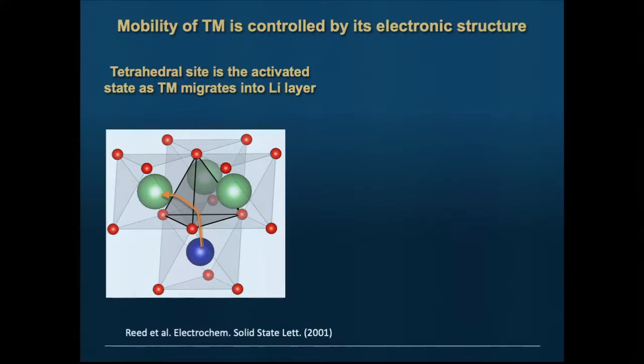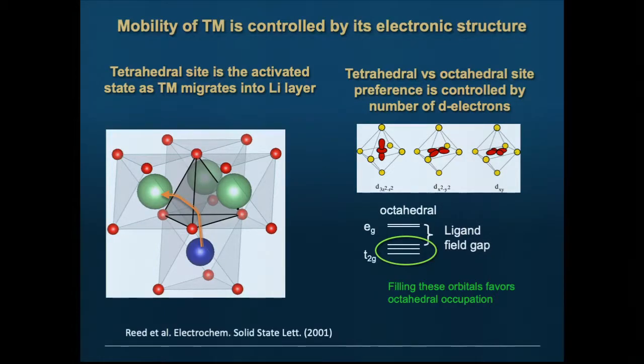So let's get to the science. Why is only cobalt, nickel, and manganese good? Well, that has to do with the mobility of these ions. It turns out that some have a much easier time to migrate from one octahedral site to another. And remember, I told you they have to go through the tetrahedral site. So it turns out the activation energy for metal motion, not the lithium, for the transition metal motion, depends on its electronic structure, because it depends essentially on how ambivalent the ion is about its coordination. It sits octahedral. If it doesn't mind being tetrahedral, then it's going to easily migrate through, because it has to go through a tetrahedral site.